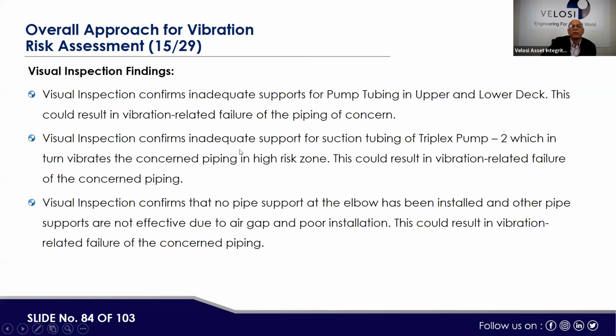Visual inspection confirms inadequate support for suction tubing of Triplex Pump – 2, which in turn vibrates the concerned piping in a high risk zone. This could result in vibration-related failure of the concerned piping. Visual inspection confirmed that no pipe support at the elbow has been installed and other pipe supports are not effective due to air gap and poor installation. This could result in vibration-related failure of the connected piping.